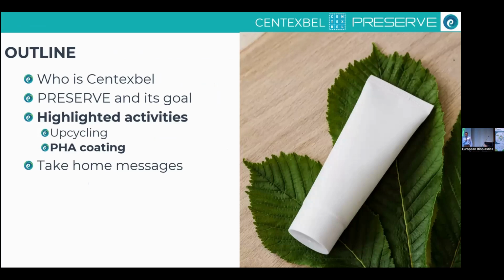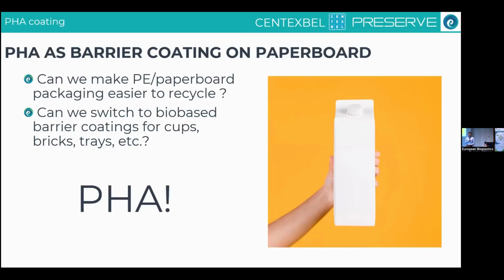Then the second aspect that we performed at Centexbel is related to coating activities, and more specifically coating of PHA. The goal here is: how can we make traditional polyethylene paperboard packaging easier to recycle? And also, can we switch to more bio-based solutions, so can we replace this polyethylene by a bio-based material? In this sense, PHA is quite an interesting material because it is already known from articles that it can have quite good water vapor transmission rate barrier properties. So it's very interesting for these kinds of bricks, cups, trays, etc., as a barrier layer.